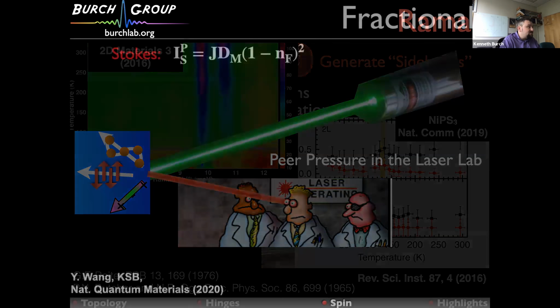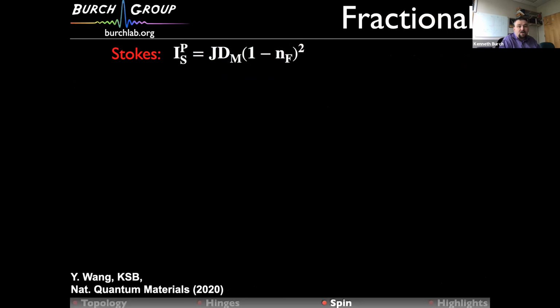All right, so what did we do in ruthenium chloride? We wanted to show that the excitations we were seeing were really fractional. So we realized that the response should be basically a joint density of states of these Majoranas times 1 minus a Fermi function squared. And the reason for the squared is, again, that you're creating pairs of Majoranas in this system.